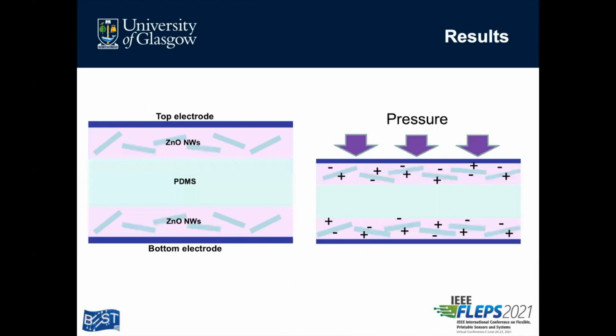To take advantage of the piezoelectric effects, during fabrication, we placed the zinc oxide nanowire layers closely next to the electrodes to enhance the electrical connection from the electrodes to the dielectric material. And under the influence of a vertical pressure, the drop-casted zinc oxide nanowires become polarized and more compact. At the same time, the introduced charge carriers are generated because of the polarization effect. Then it sequentially interacts with PDMS and therefore strengthens its dielectric property.